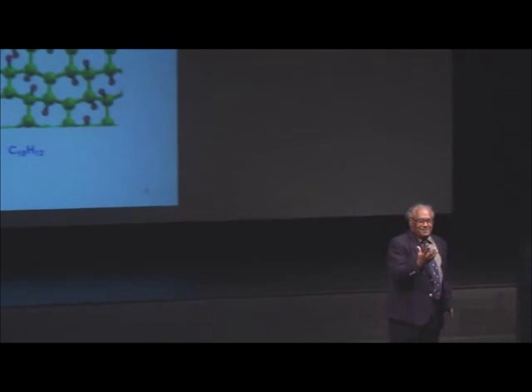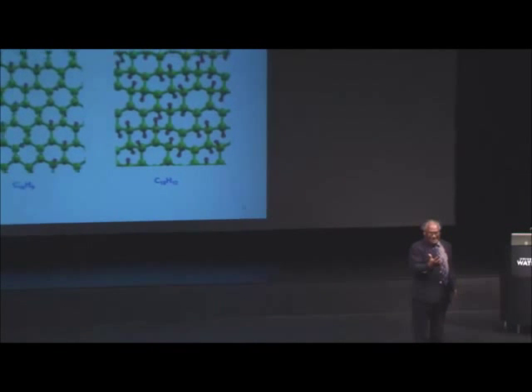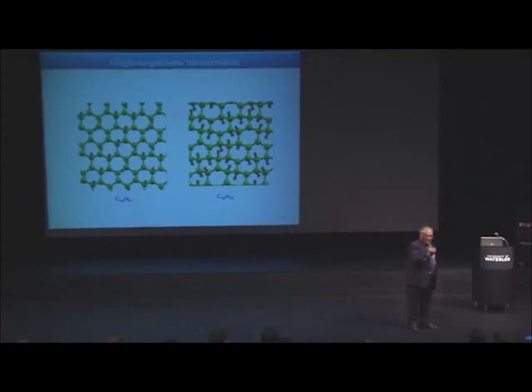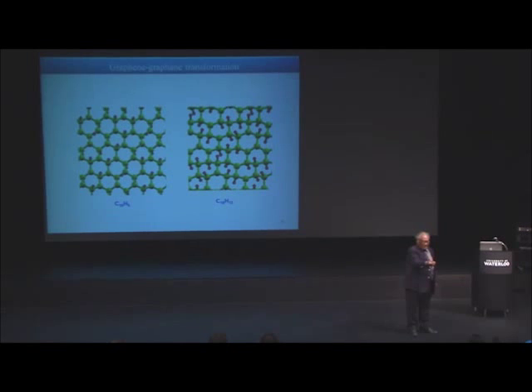Now, we have got up to 5.5 weight% hydrogen on graphene. What is amazing is that it comes off. That hydrogen which forms CH bonds, as I follow the infrared spectrum, the CH bands around 2,900, 2,850 reciprocal centimeter, as I go on heating it up to 400, all the hydrogen comes off. And that has been very heartwarming for me. Here is a wonderful reversible hydrogen source which comes off just by warming.